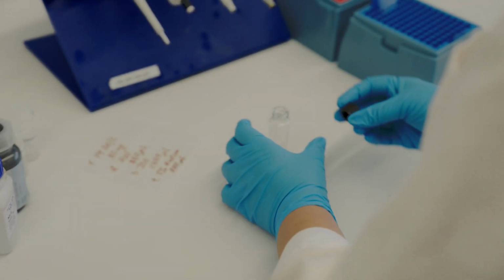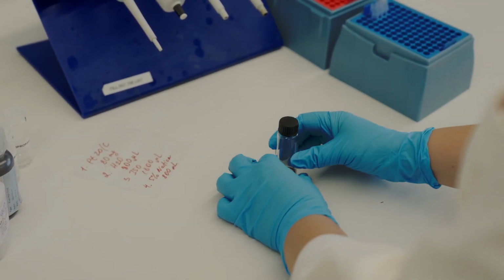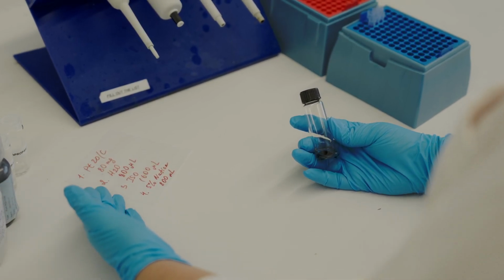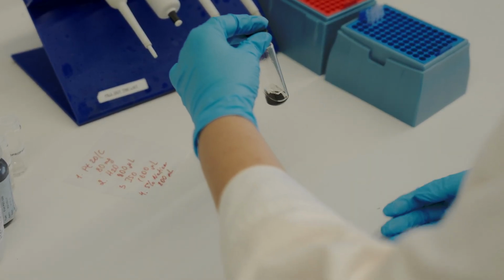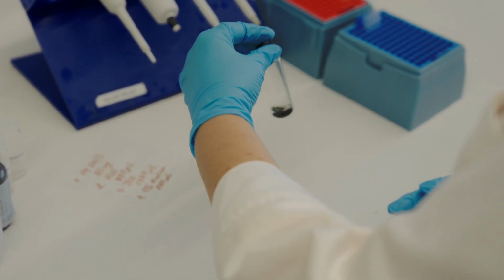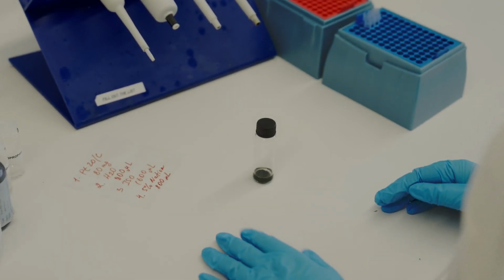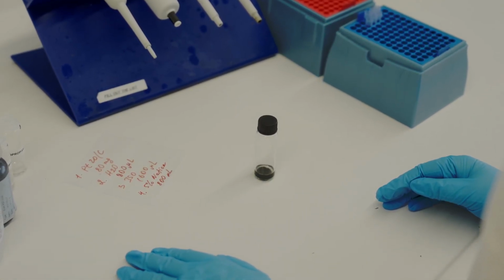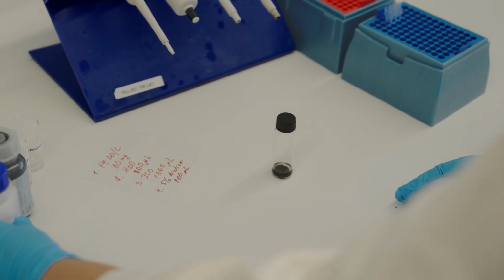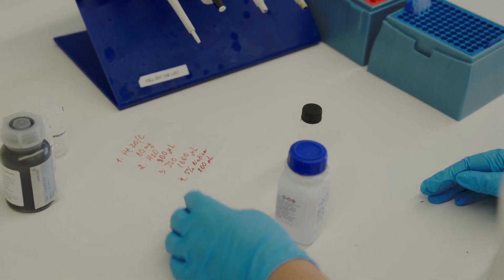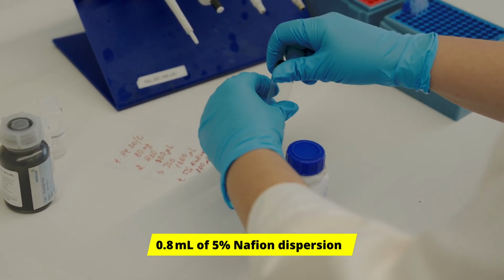At this stage, we seal the mixture to mimic the standard situation in which Nafion dispersion is stored in a refrigerator, and to prevent alcohol components from evaporating from the mixture. When you are ready, add the final component, 0.8 ml of 5% Nafion dispersion.